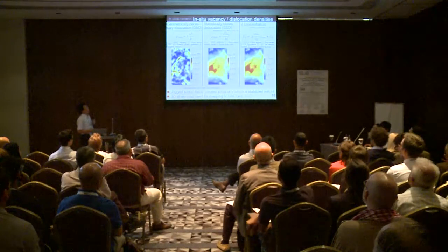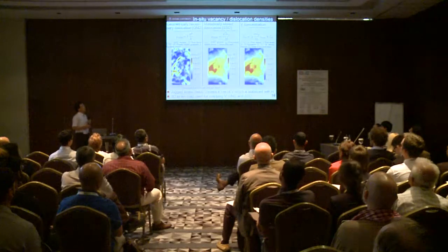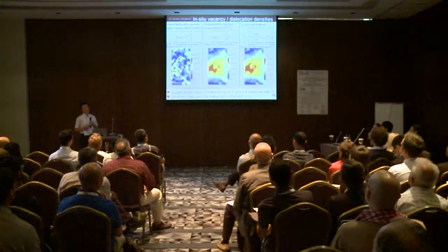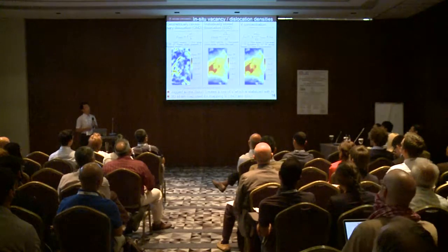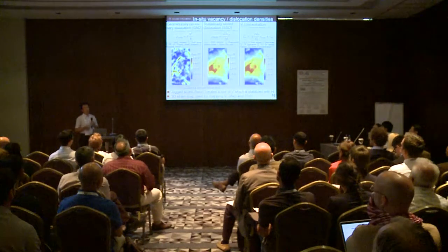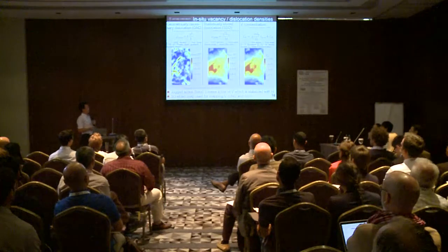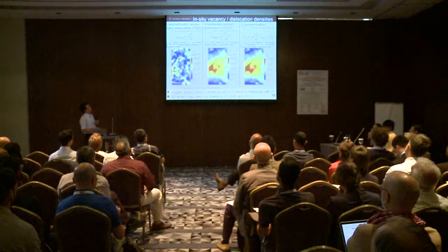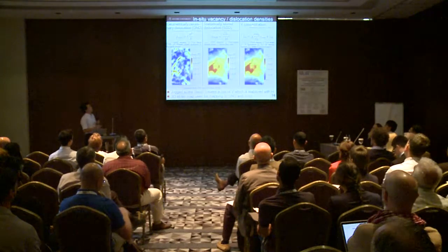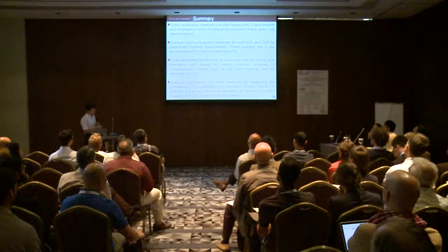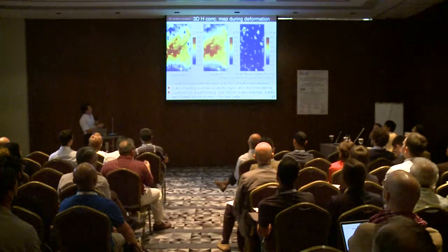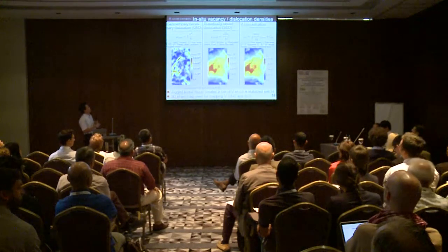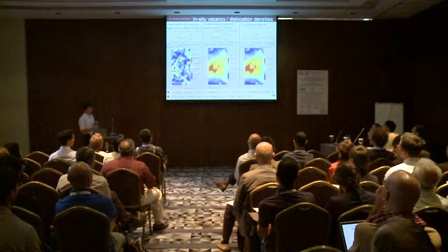deformation. And in this case, we don't assume the annihilation of vacancies, because vacancies can be stabilized instantaneously due to the existence of hydrogen. So anyway, we can see very high SSD and vacancy concentrations where strain is localized, and GND density is very high in the peripheral region.